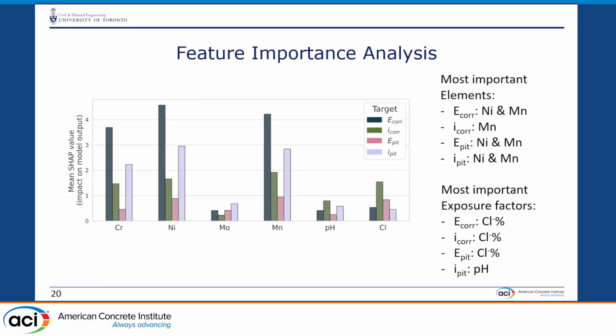If you base your ranking on E-corr, you will find nickel and manganese to be more sensitive to that ranking. If you base it on I-corr, manganese is a lot more sensitive to that. If you base it on pitting potential, nickel and manganese are more sensitive. The same thing goes for chloride and pH. Chloride is more sensitive to E-corr, I-corr, E-pit, and then pH.